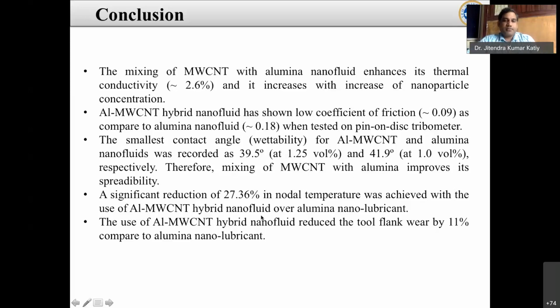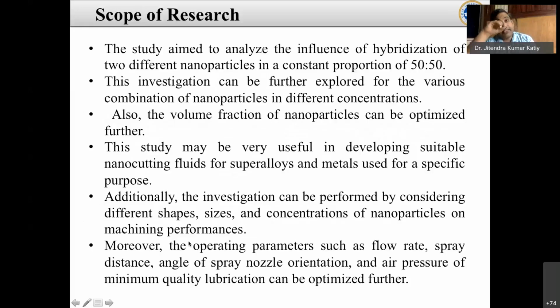So overall, we observed a significant reduction of 27.3% in the nodal temperature in the case of the hybrid cutting fluid, and an 11% reduction in the flank wear in the case of the hybrid nano cutting fluid, aluminum and multi-wall carbon nanotube. So in this type of work, various scope of research is still there. You can easily get good publications in this area.